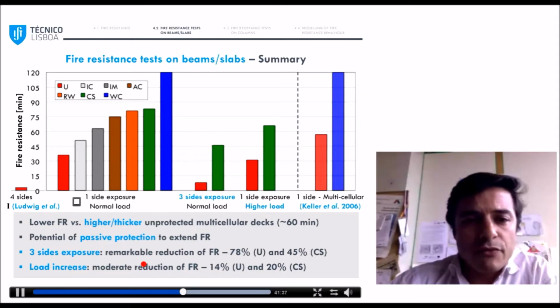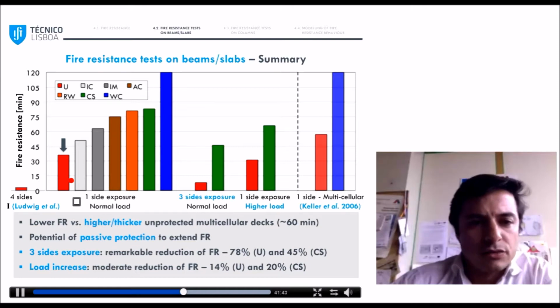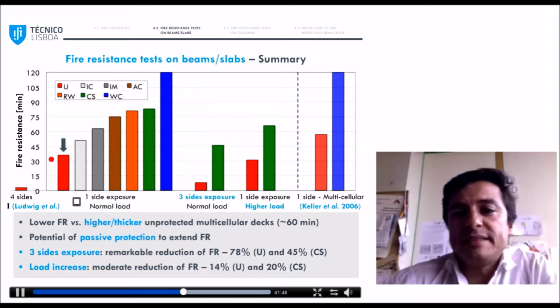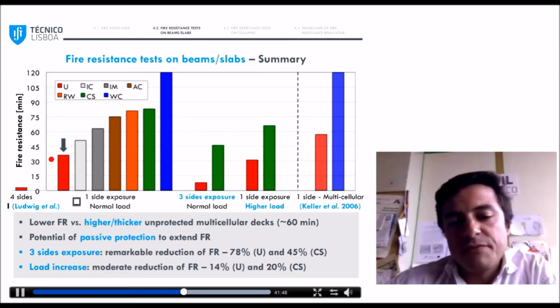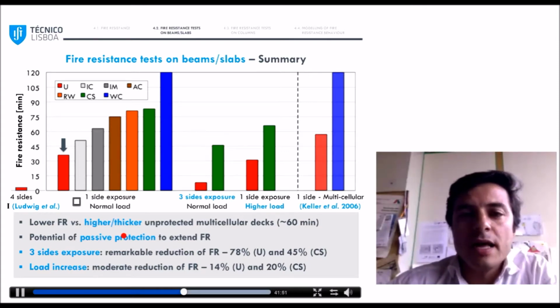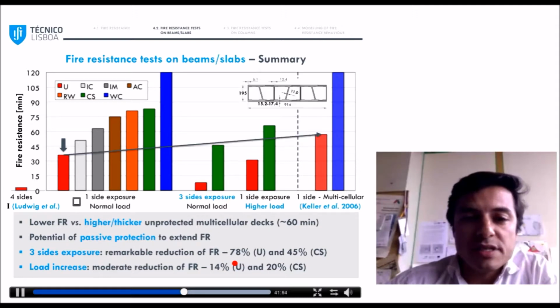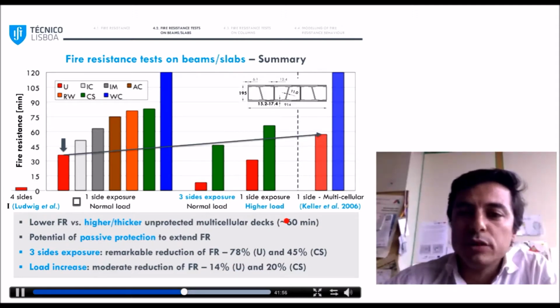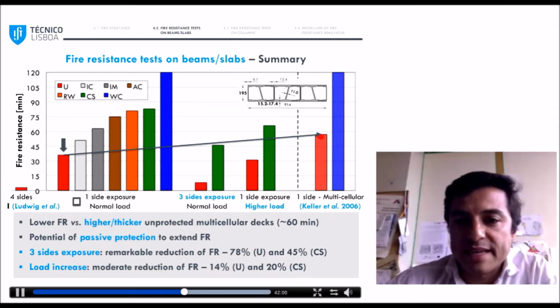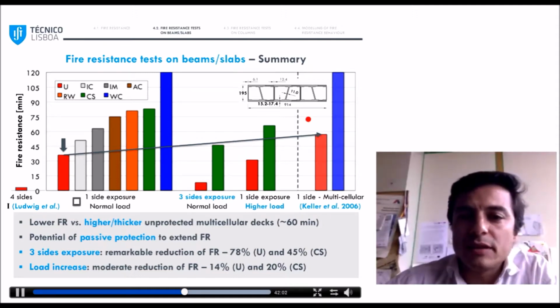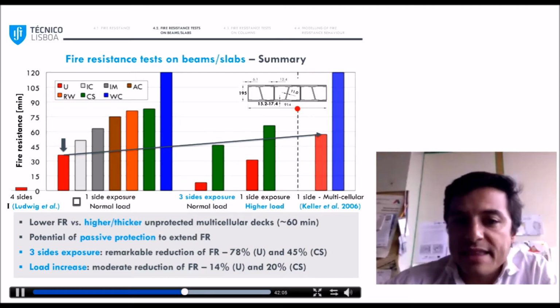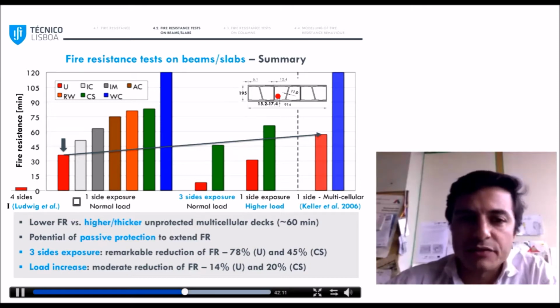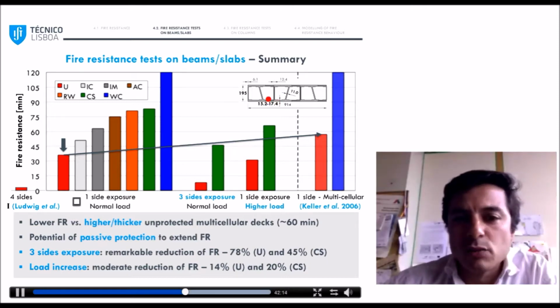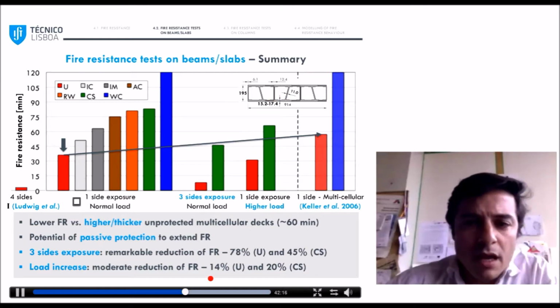So first of all, for the unprotected beam under one side exposure, so this one, you can see that the fire resistance was just a few minutes more than 30, okay? And you can see that the performance was much worse than multicellular panels that had been tested at EPFL, which resisted almost 1 hour. But I must say that these panels were much higher, okay, about 20 centimeters instead of 10. And their wall thickness was also much bigger.